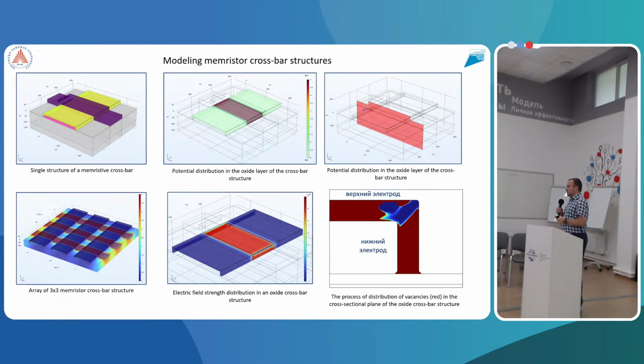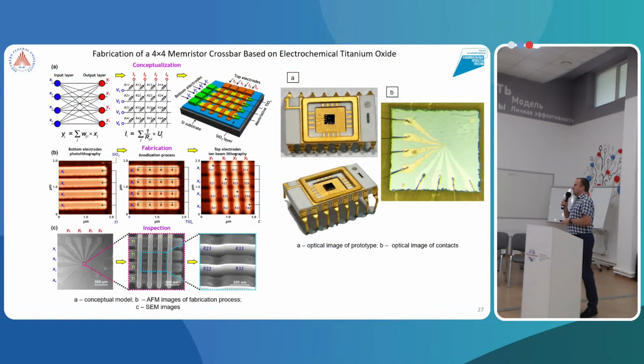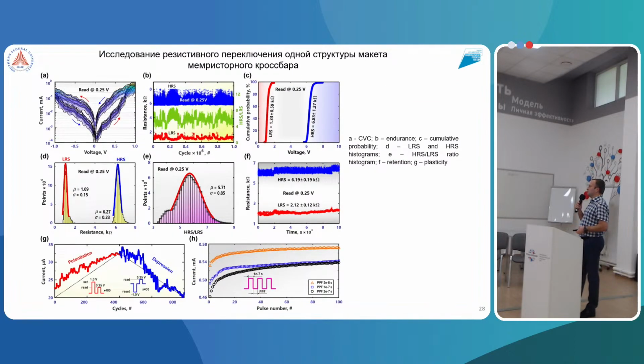Also, we simulate the physics of resistive switching in crossbar structure by using COMSOL Multiphysics software. Here we can see different processes of resistive switching, the distribution of vacancies in the cross-sectional plane of the oxide crossbar structure. After that, we fabricate the prototype of memristive crossbar based on electrochemical titanium oxide and investigate their main properties presented on this slide.